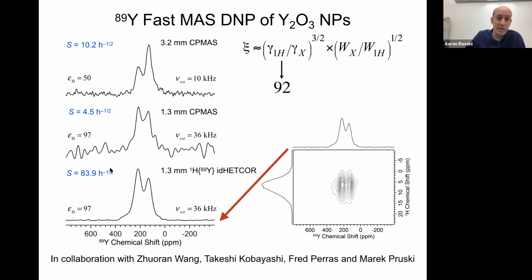But now if we do the proton-detected yttrium-89 experiment with the idHETCOR pulse sequence, we can get a factor 8 net improvement in the sensitivity over the 3.2 millimeter rotor. So this is nice. You've really cut down on the amount of sample. You only need a couple milligrams of sample for the 1.3 millimeter rotor, and the proton detection really does provide good signal gains for these low gamma nuclei.